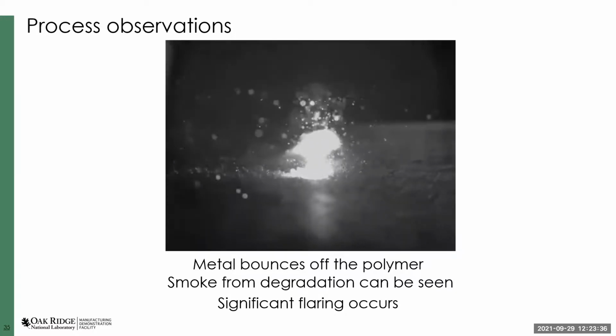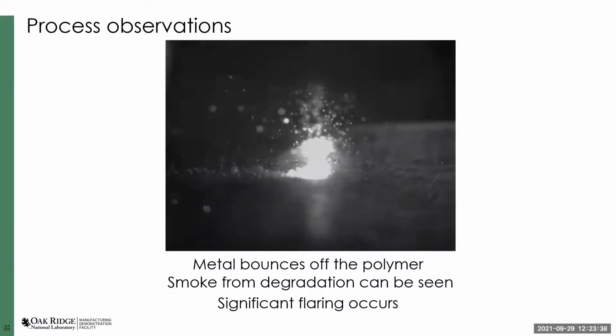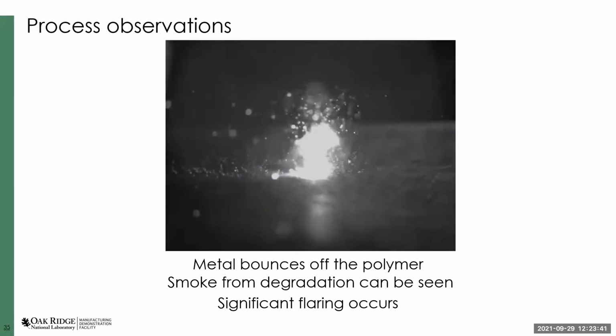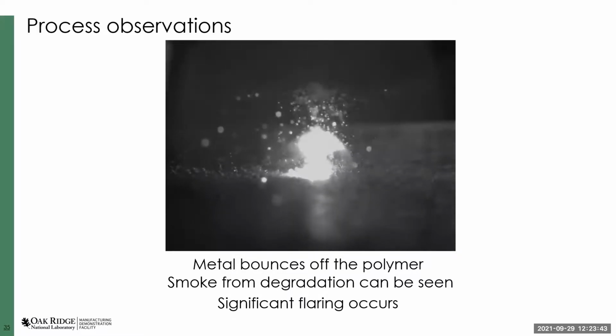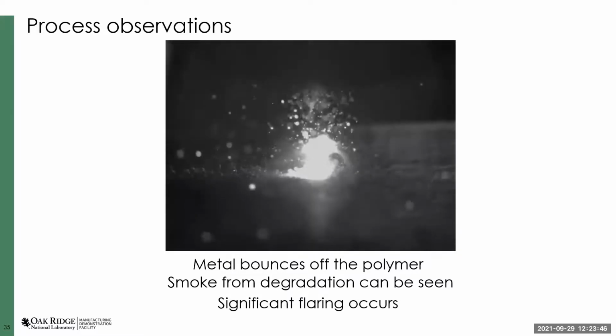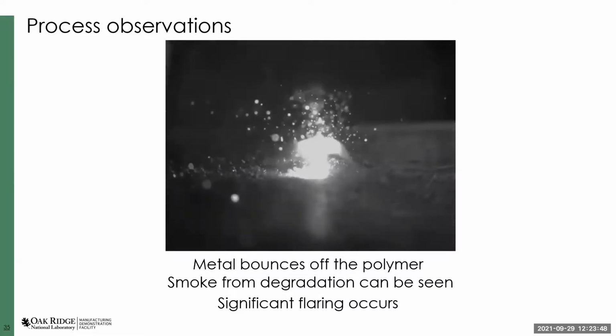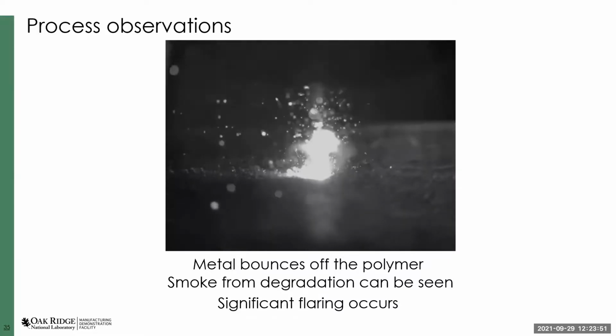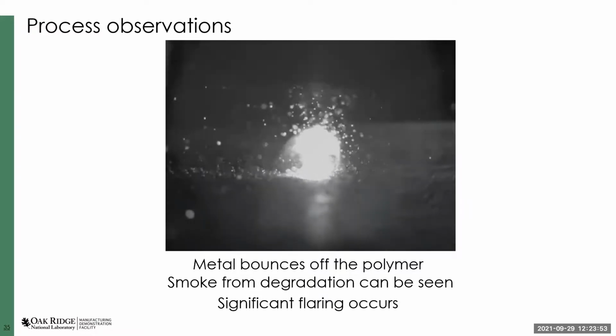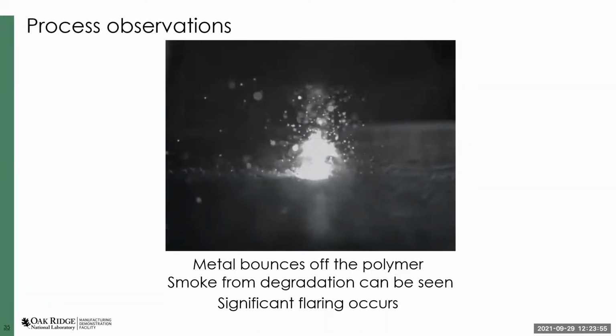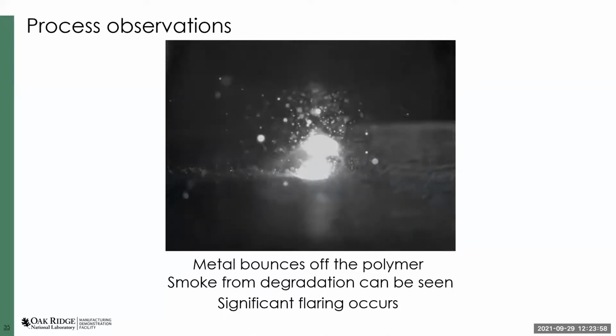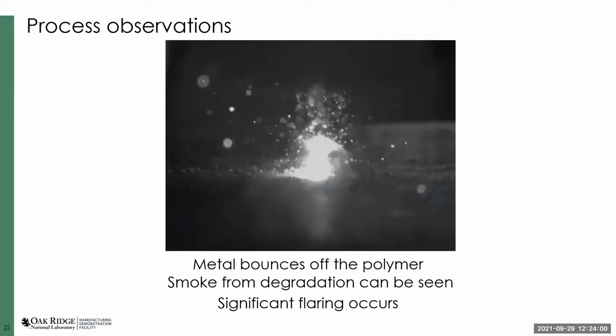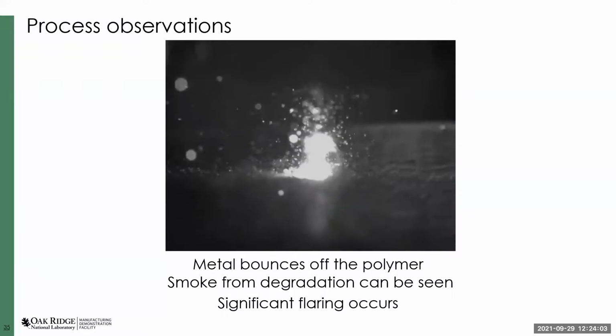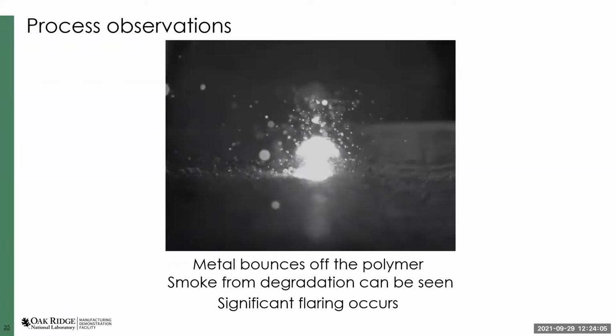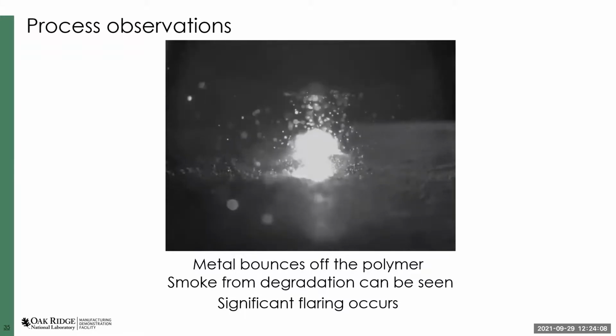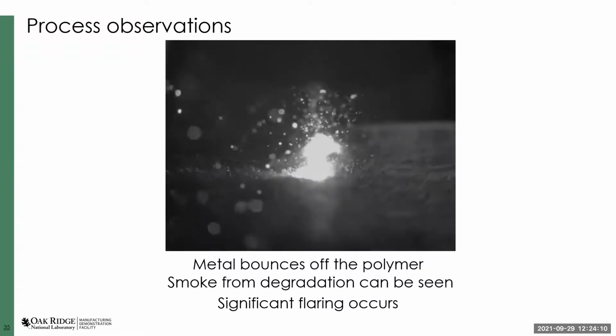I don't know if any of you have a lot of experience with carbon fibers, but metal does not tend to wet carbon fiber very well. So this makes sense. And a key observation here is that you can see a lot of smoke coming off. You can see almost this plume coming off of the polymer as it's interacting with the DED process, which indicates that our hypothesis about a thin layer of polymer degrading is correct, because that smoke, that residue, is an indication that the polymer is burning off and creating some kind of gaseous residue.